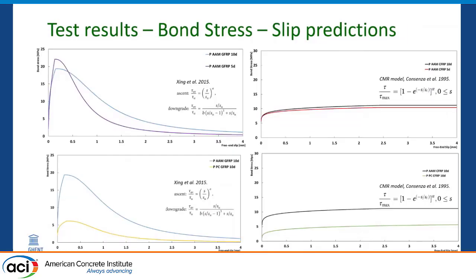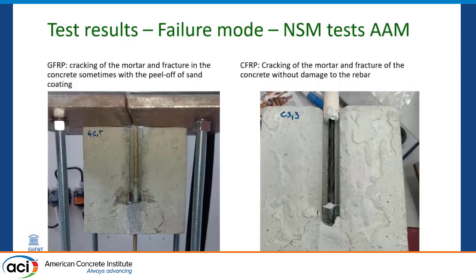So here we can see the bond stress slip predictions, where for the alkali-activated mortar and GFRP, the closest approximation was with the model published by Xing et al. in 2015 with a strengthening and downgrading part. The similar is for the PC mortar and GFRP, while for the CFRP and the alkali-activated mortar, actually the CMR model from Cosenza et al. in 1995 was proposed, was the best. The same is for PC and CFRP bars.